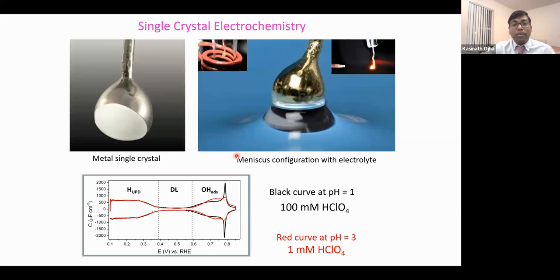So I started doing experiments on that. This is single crystal electrochemistry. We have an electrode, we have single crystals of platinum, and we cut a particular surface. For our experiment, it was the 111 surface. So we get only a surface that has the 111 structure of platinum atoms. And we do electrochemistry in a meniscus configuration with the electrolyte, where only that cut surface is exposed to the electrolyte. The other surfaces are not touching the electrolyte at all. So whatever electrochemistry and ion interactions are happening, they are happening only at that particular surface, not the other surfaces. This is typical single crystal electrochemistry people do.